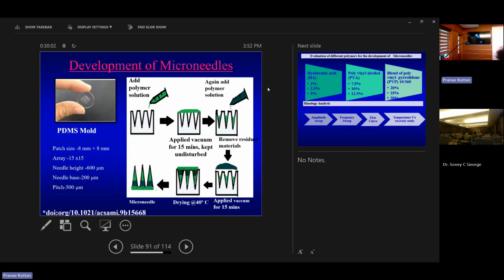So how do we develop this microneedle? There is a mold called PDMS, polydimethylsiloxane mold, and this can be purchased. We can make it also, but we purchased it because we wanted very proper dimensions. We purchased this kind of dimension. The needle height was 600 micrometers, and this is the cross section of the mold, and we can add polymer solution into it.